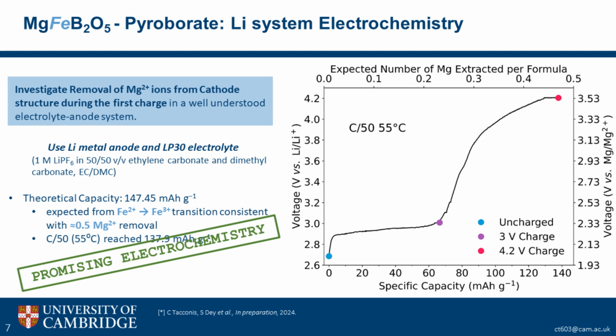And so if one looked at just the electrochemistry, it would look really promising. We've got a nice plateau here around 3 volts, and it looks like we're getting almost all our theoretical capacity. But what we wanted to do was to go really in depth and see whether we were removing magnesium from the cathode. And the magnesium removal would be accompanied by an iron redox process. And so we decided to use Mossbauer spectroscopy to investigate whether we were seeing this iron redox process. And so now this is a slide on Mossbauer spectroscopy.